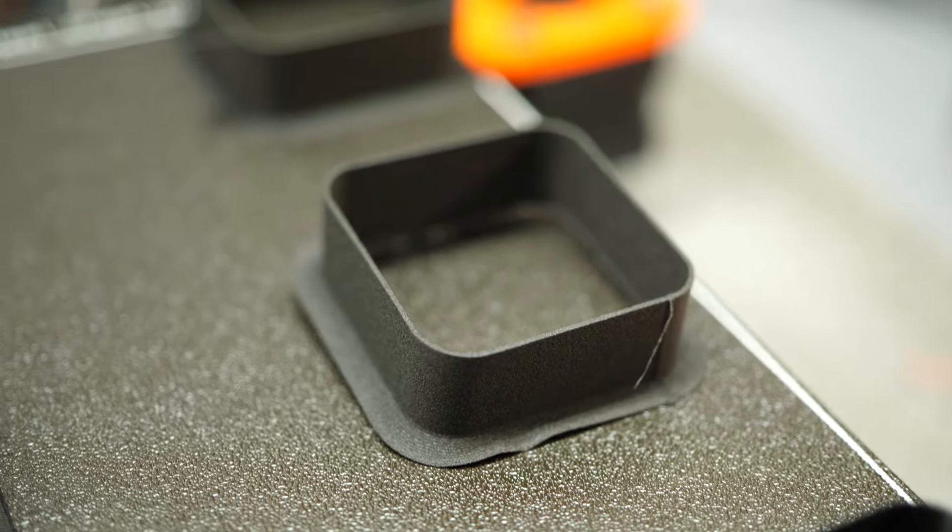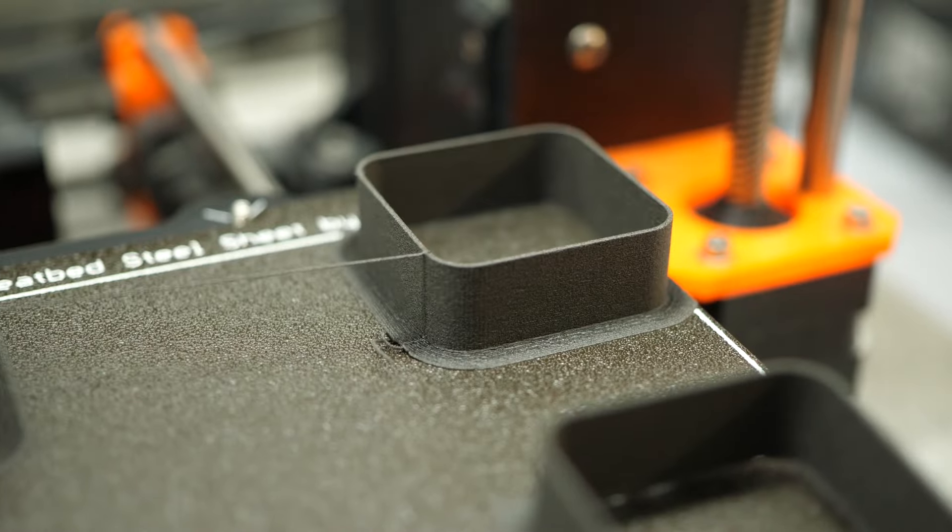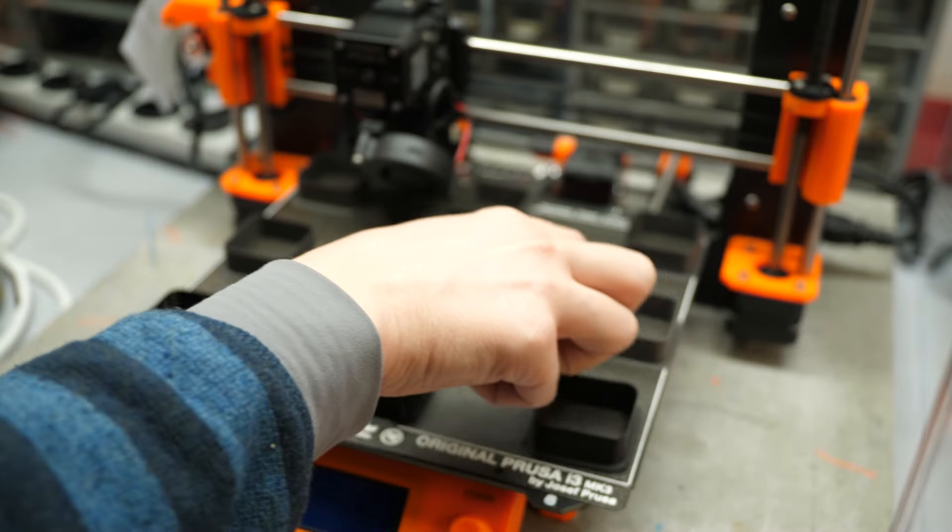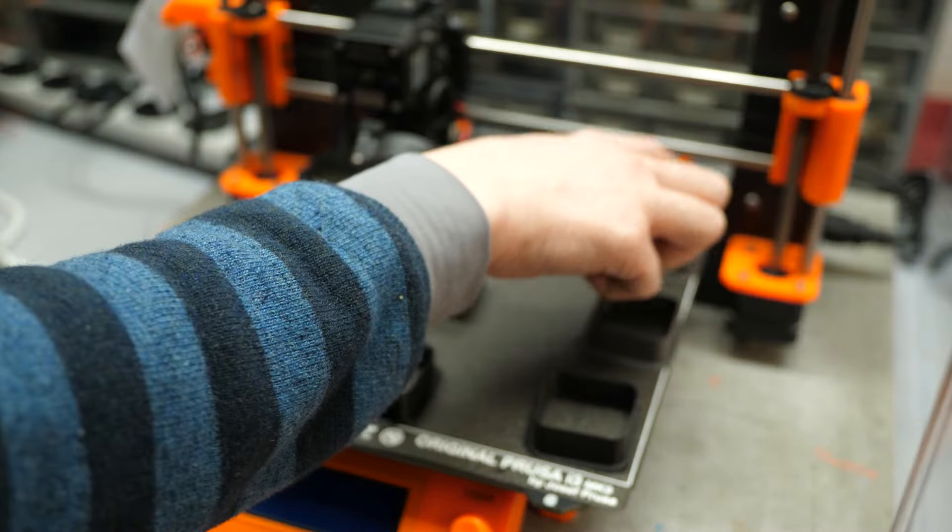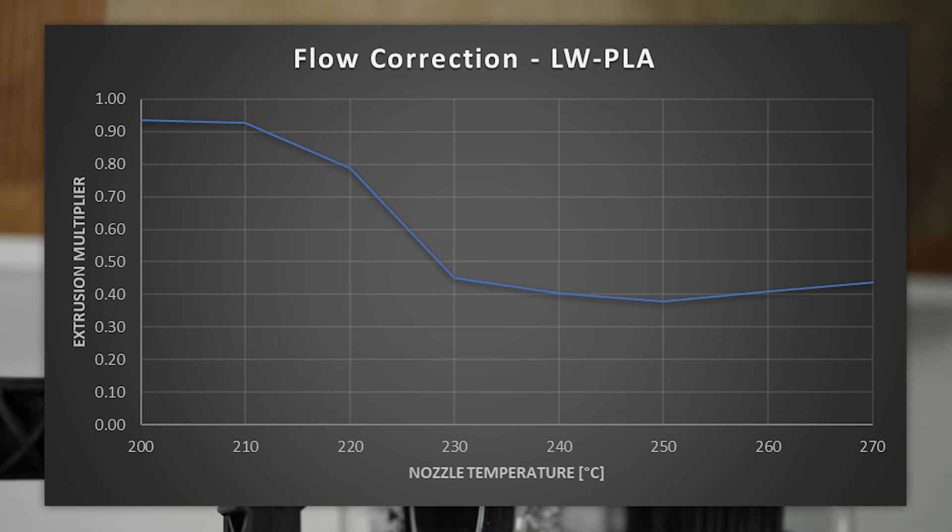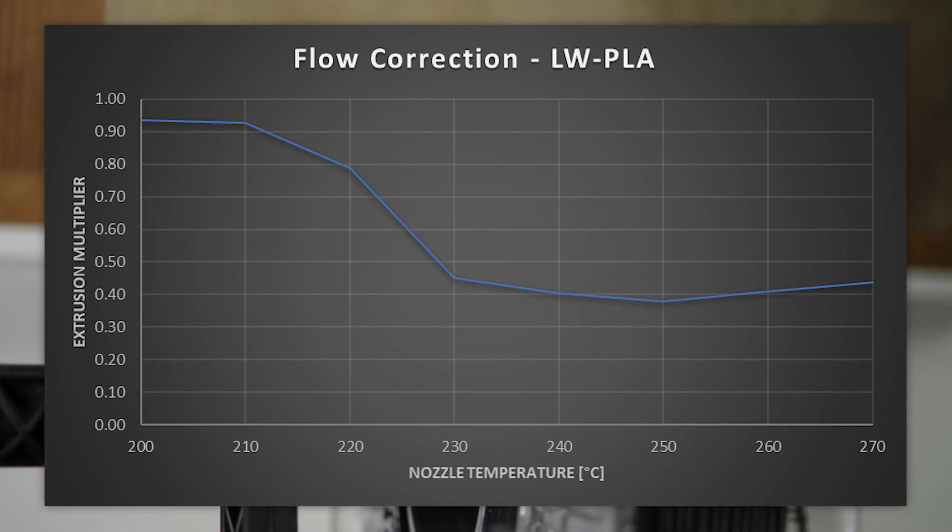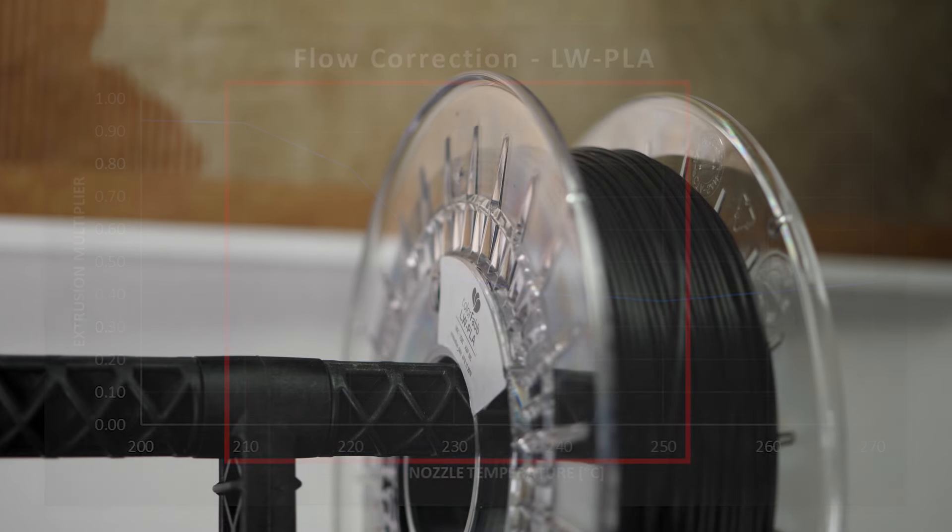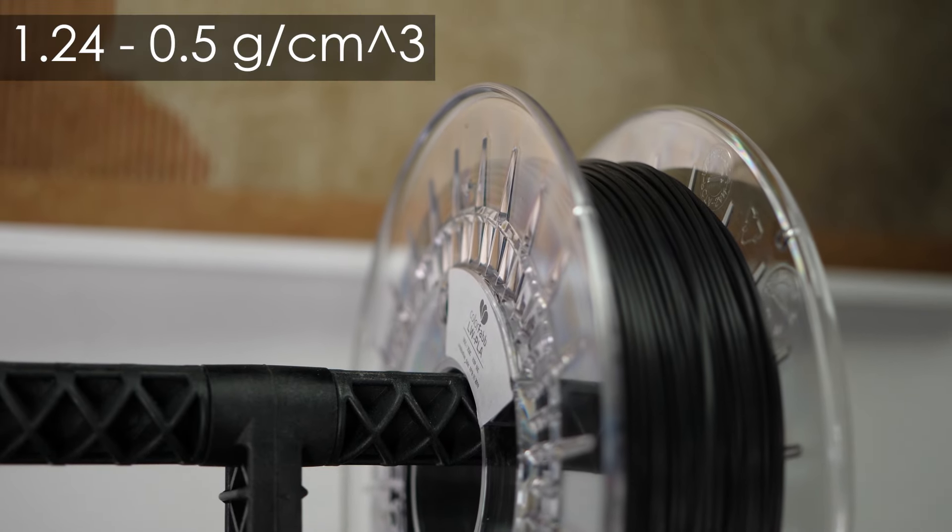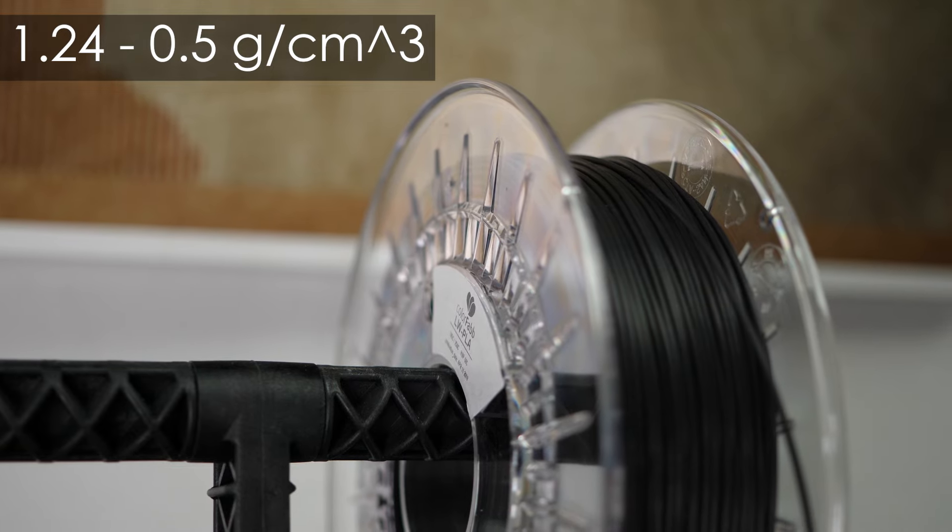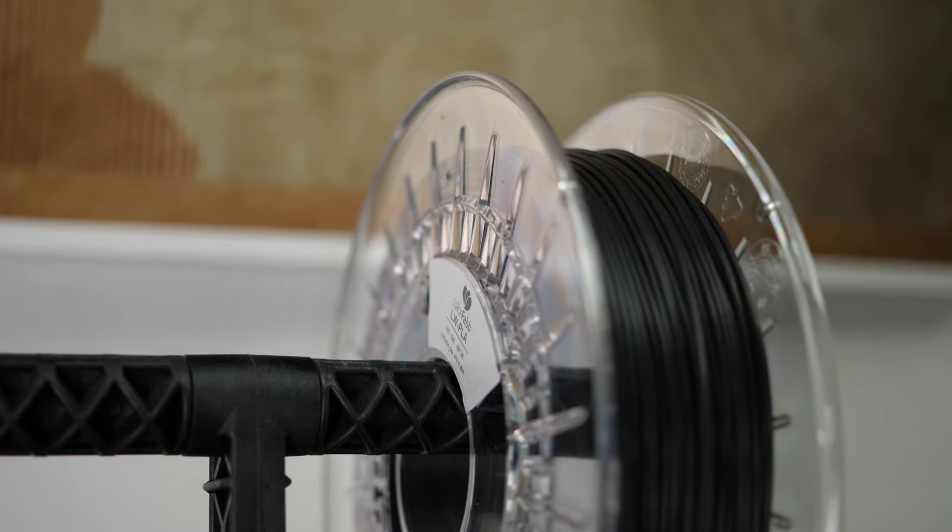The difference in density and stiffness can even be heard if you pluck the printed part. In the end, I produced a nice graph that shows that at around 215 degrees Celsius the foaming starts and at around 240 degrees Celsius or 250 degrees Celsius you reach the maximum. This is basically the range in which you can play to adjust density. I didn't reach three times the volume but more than two was possible which is a reduction to around 44% the density of regular PLA.